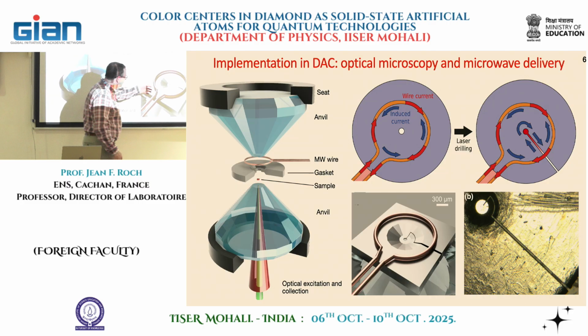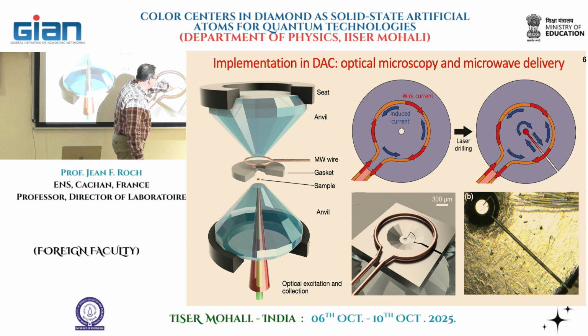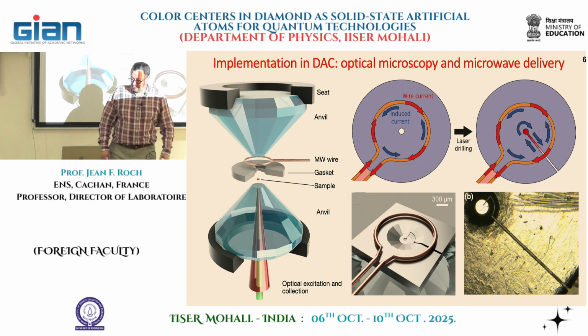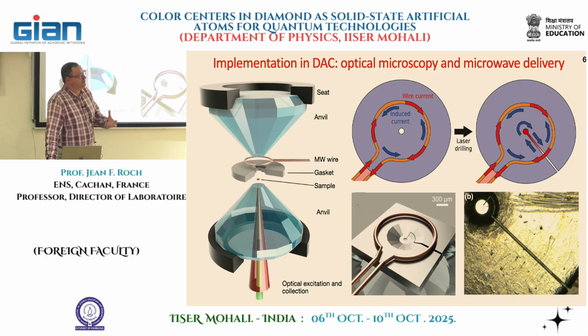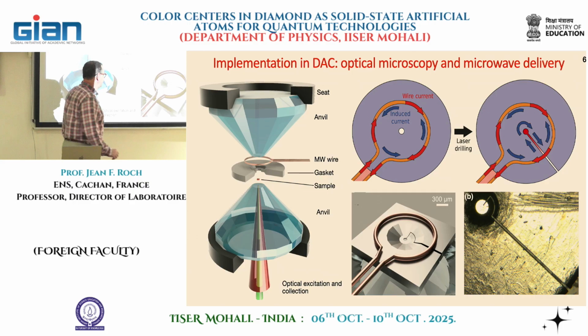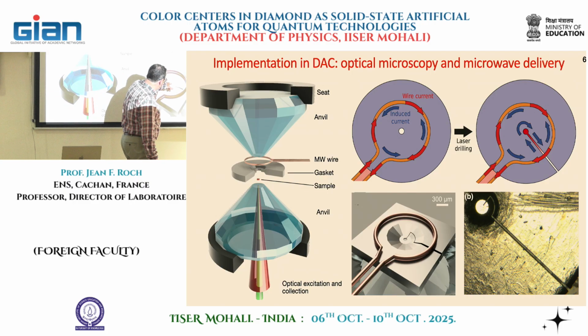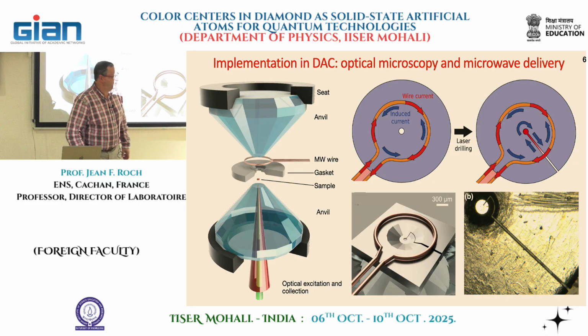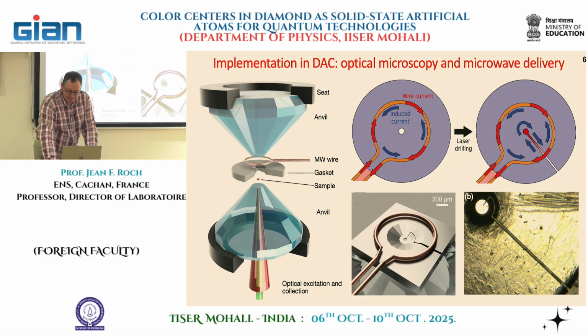So we worked a lot on optimizing the design of the slit, and we found that somehow with this shape we can go up to more than 100 gigapascal with a very stable shape of the slit. And the slit is cut with a femtosecond laser. So we have a femtosecond laser, and we can design the shape of the slit that we want using this system. OK, and then you see here, again, another view of the slit cut in the metallic gasket.